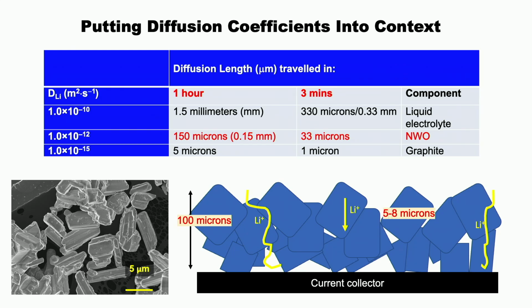So let's just reflect for a few minutes on what that means. So let's compare our materials with the common other conductors. So if you're a liquid electrolyte, your diffusivity is about 10 to the minus 10. So if you're trying to do a 3-minute charge, it means you can move about 330 microns in those 3 minutes. So you can move from one side to the other side of a battery. So battery electrodes are about 150 microns or 100 microns, depending on whether you're optimizing for power or energy density. But if you're a graphite, and this is the 10 to the minus 15 that I showed you earlier in the talk, that means that in 3 minutes you can only move a micron.